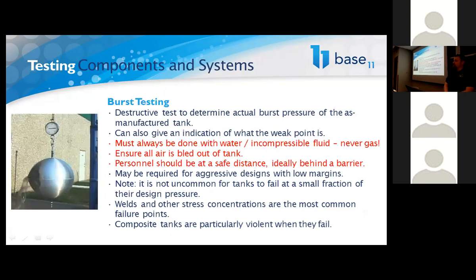So the other type of testing that you might want to do on a tank that you've developed yourselves is going to be burst testing. It's one thing to design a tank for a particular burst pressure, but it's very, very common to have pressure vessels fail, especially at the welds, at a small fraction of the pressure it was designed for. So if you're trying out a brand new design, it's a really good idea to try burst testing on it, which looks an awful lot like proof testing, except you take the pressure higher to the point where the tank fails, and you see where that actually is.